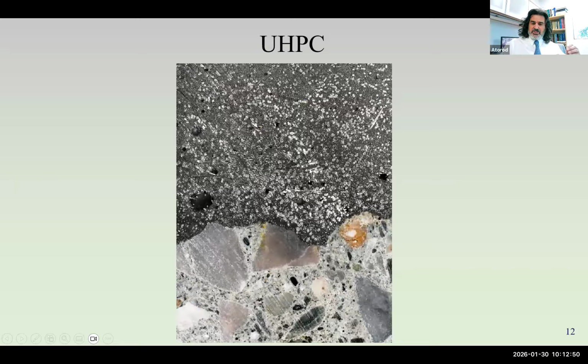As you can see, there is no coarse aggregate. There's lots of steel fibers. In fact, if you look, you can see maybe some steel fibers here. In fact, 1 cubic yard of UHPC uses about 250 pounds of steel fibers. These steel fibers are 13 millimeters in length, 0.2 millimeters in diameter, and they're 400 KSI.